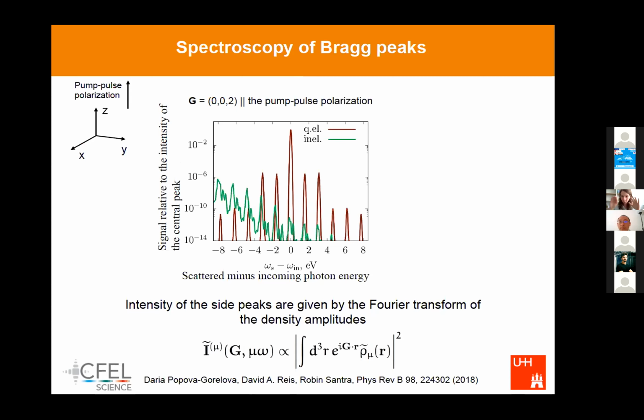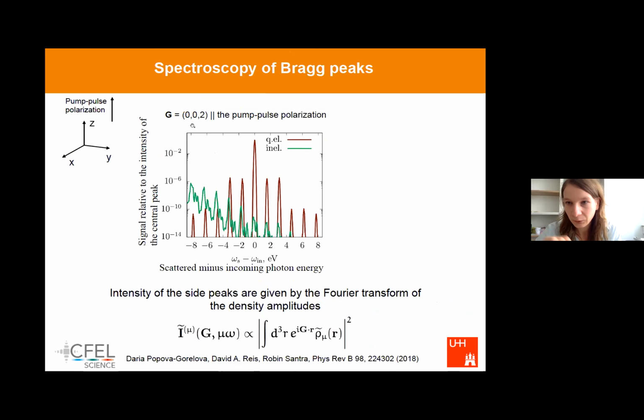And then what we propose is that we not just look into the scattering angle, but we also do the spectroscopy of all photons in this scattering angle. So in the case of field-free magnesium oxide, there will be a large elastic Bragg peak, and there would be some inelastic scattering.